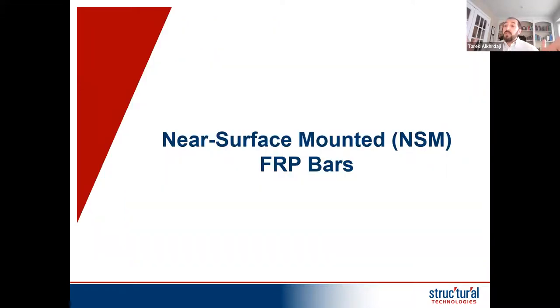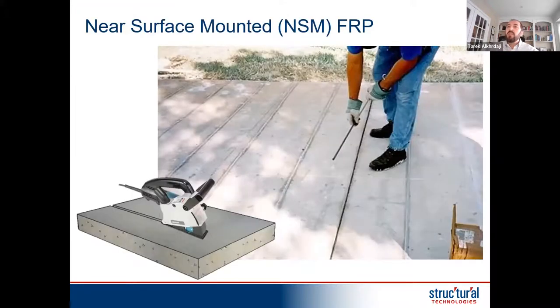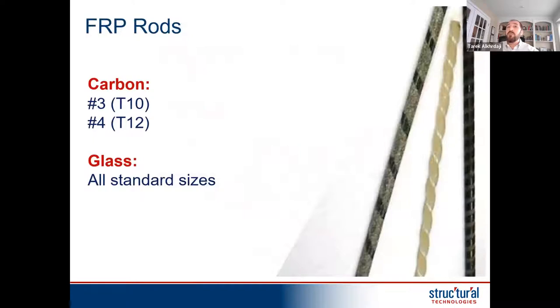Another technique besides this fabric that I described to you is what we call near surface mounted FRP bars, or surface embedded FRP bars. This technique depends on, rather than bonding the carbon fabric to the surface, we cut a groove into the surface and epoxy in carbon bars. These are round bars that come in different sizes. The most common ones that we use for strengthening applications are equivalent to T10 and T12 in terms of diameter, right? Of course, they have different properties, but only equivalent diameter. In the US, they call them number 3 and number 4 bars, the 3/8 and 4/8, which is half an inch bars. And that's in carbon.